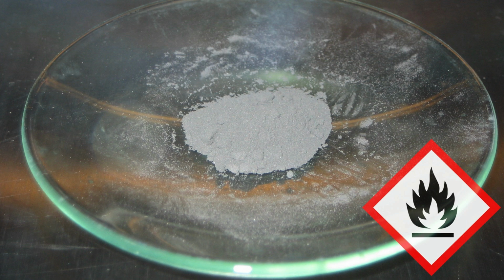Since nickel is the active metal of the catalyst, a large nickel surface area implies that there is a large surface area available for reactions to occur simultaneously, which is reflected in an increased catalytic rate. Commercially available Raney nickel has an average nickel surface area of 100 m² per gram of catalyst. High catalytic activity, coupled with the fact that hydrogen is absorbed within the pores of the catalyst during activation, makes Raney nickel a useful catalyst for many hydrogenation reactions.